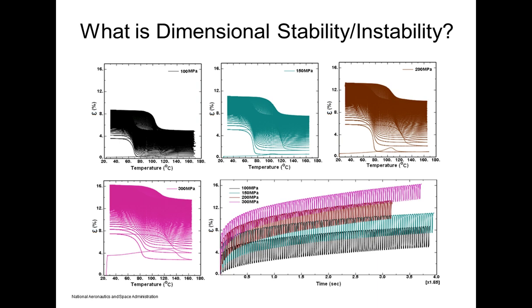But for the nickel-rich side of the shape memory alloy systems, where we're heavily using aging to heavily precipitate things, there are differences that will happen in terms of reductions in ductility limits that we can use in order to drive these states. And so only from that perspective do I think that there is potentially an issue, in the sense that once we have highly precipitated systems, we change the characteristics of how much deformation we can put in isothermally without creating damage. So we want to obviously avoid damage within the component while processing to try to achieve dimensional stability for the actuator system. So in those regards, yes, there are some differences.